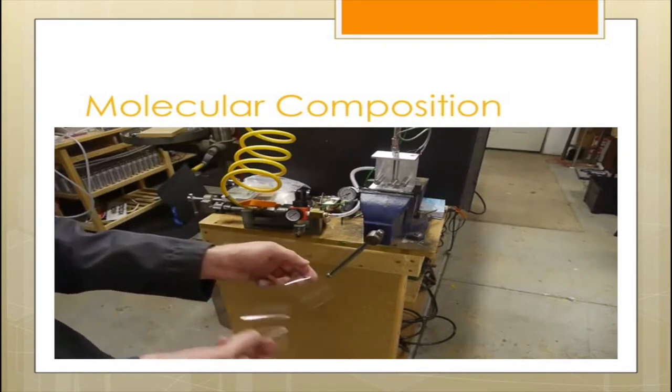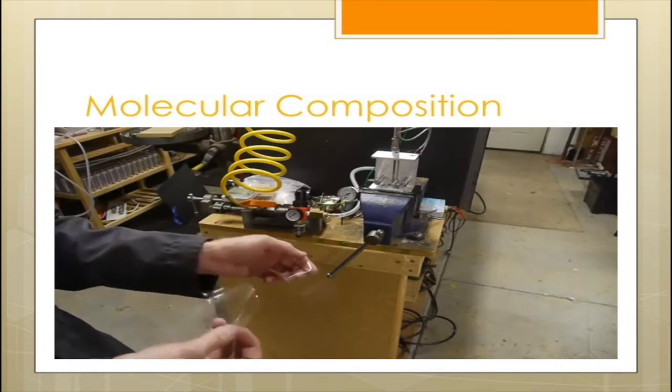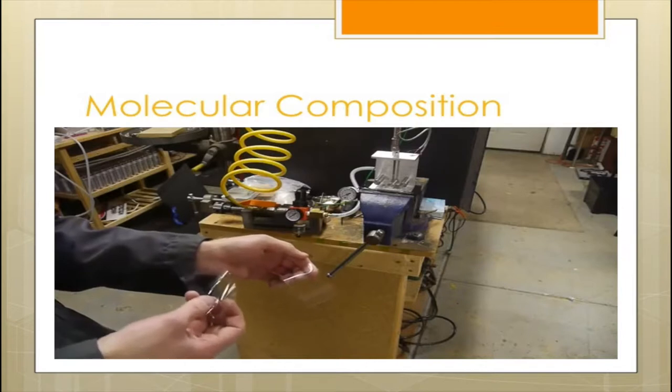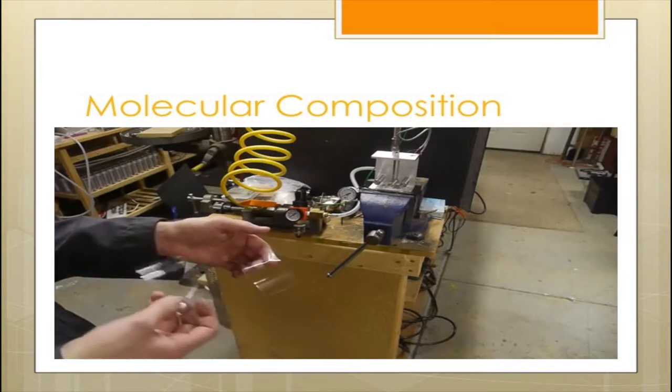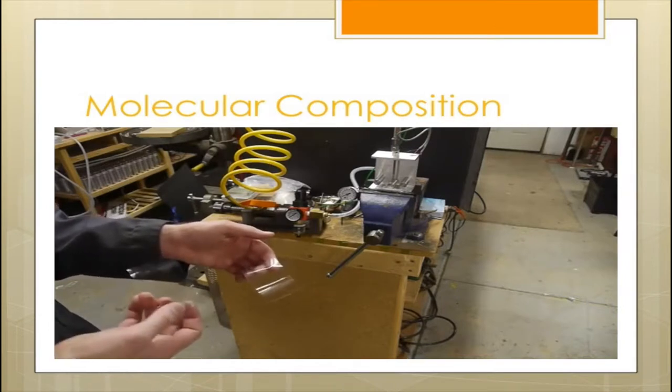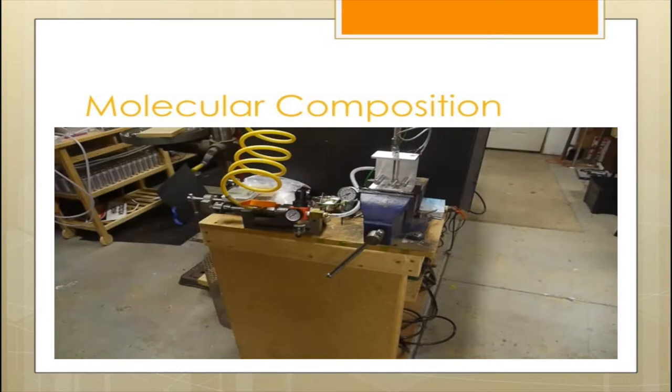But remember, in materials like glass, there are a huge number of defects in all pieces of glass that you'll encounter in the world. They're distributed throughout the material. So it's actually the size and the number of the defects that determine how strong a piece of glass is. If we could somehow make a piece of glass that truly had no defects whatsoever, it would be about 100 times stronger or more than most glass that we encounter in the world.